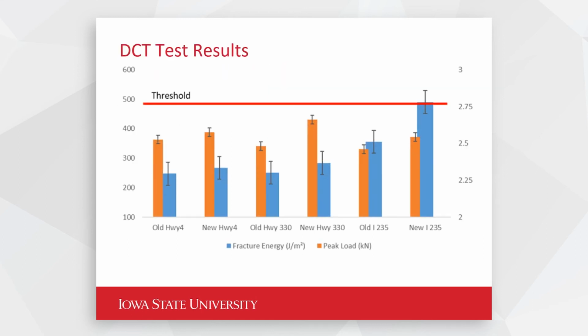Whether it's fracture energy or peak load to fracture, we see improvement there. What gets interesting here is we generally want to see our criteria at 480, 490. The threshold is shown there in red. We're now moving up and getting close to attaining that with the I-235. Keeping in mind, this was under the old binder specifications. So with the new binder specifications, we would anticipate the performance further improving. Next slide.